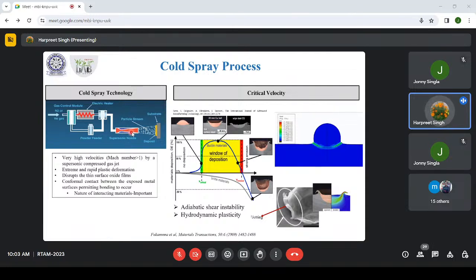Another thing we are doing is introducing the powder particles into that supersonic jet. Now, what would happen? We can well imagine that there will be momentum transfer from the gas to the particles. Those particles will also achieve very high velocities and they will go and stick on the surface, right? So this gun is then traversed, in a raster scan fashion or some other fashion, on the surface, and we will get the deposition.